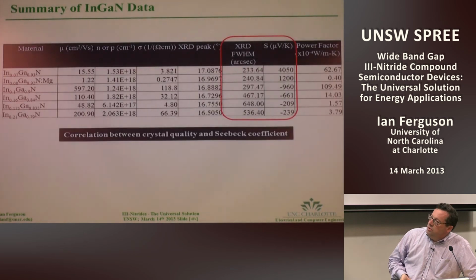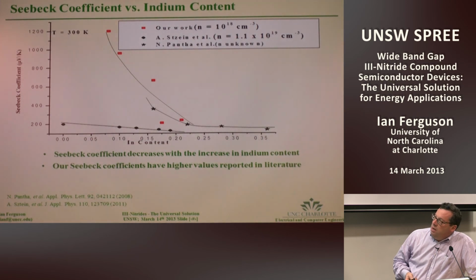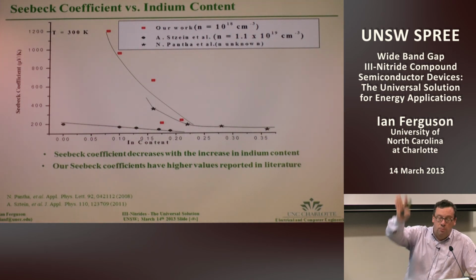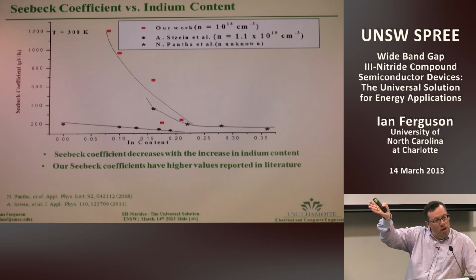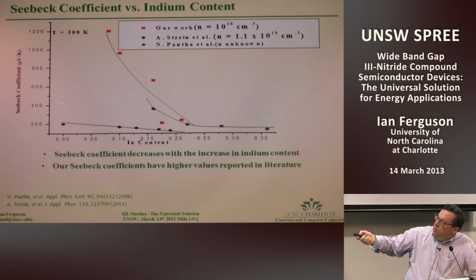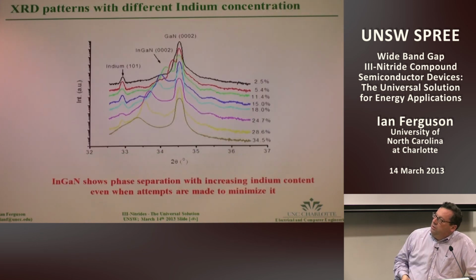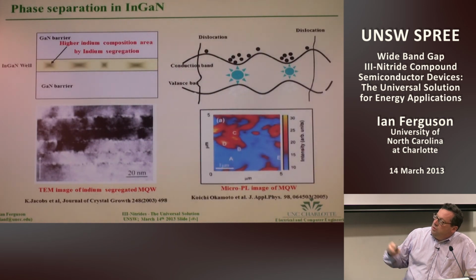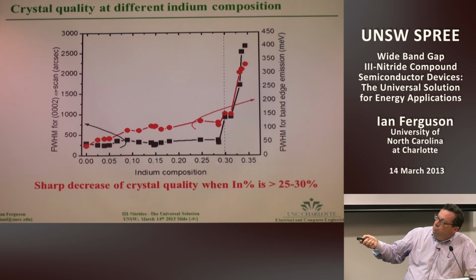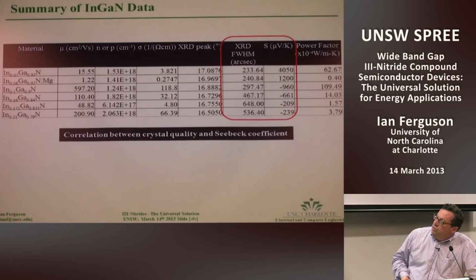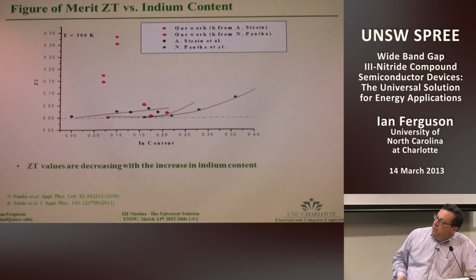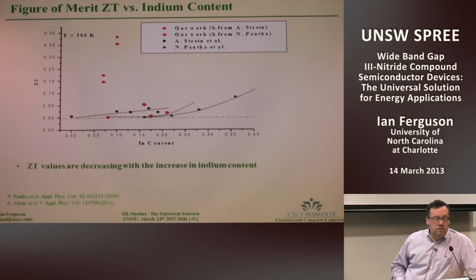Our main interest was doing this with the gallium indium nitride based materials. Because we were able to control the composition of the InGaN relative to the phase separation, as we did for the solar work, you find that most of our devices have much higher Seebeck coefficients. Then when the materials broke down due to compositional fluctuations at around 0.25, they would go back to looking like other people's materials again. You see this also with the ZT factor, which I didn't have time to talk about, but ZT is a figure of merit that tells you how good this is likely to be as a TE material.